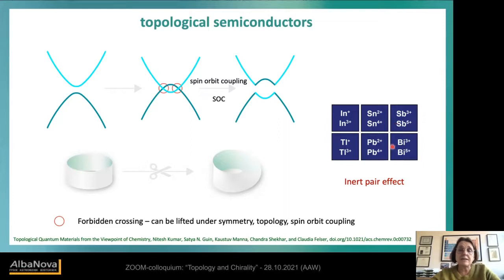So half of the elements in the periodic table have this inert pair effect, these outer s electrons which are contracted, they are lower in energy, and then the conduction band overlaps with the valence band. So it's not a rare case. But this has consequences, because now, in the case of these topological materials, the valence band and the conduction band are connected. So we have this very strange surface state, which is protected by symmetry. So we cannot destroy the surface state because this transformation is not possible.